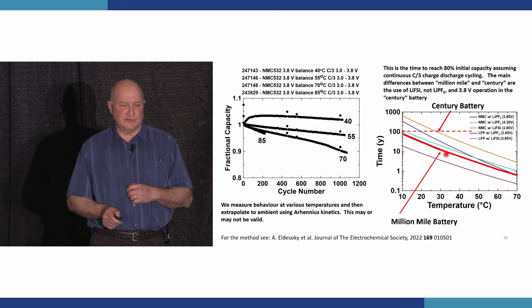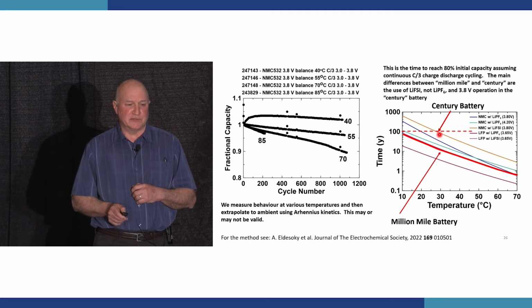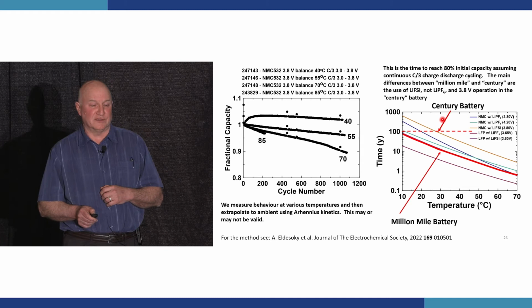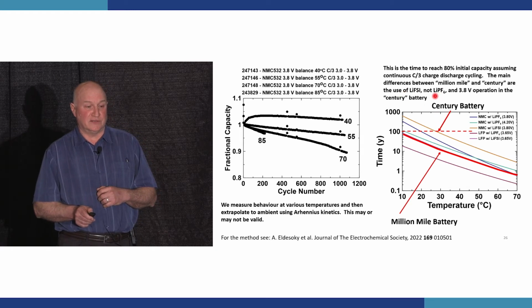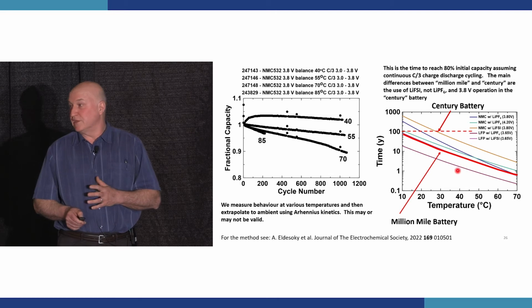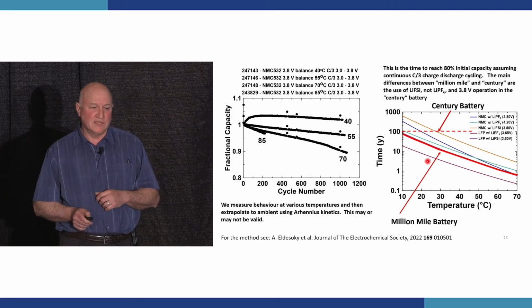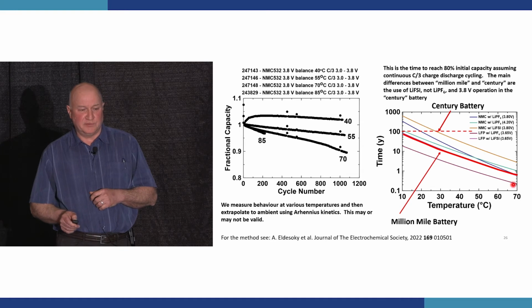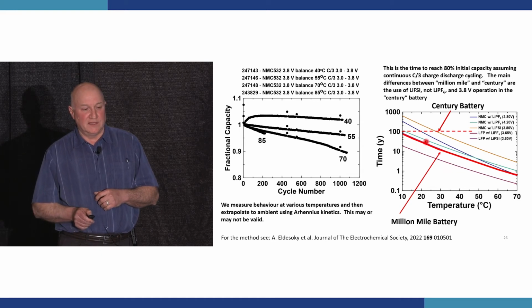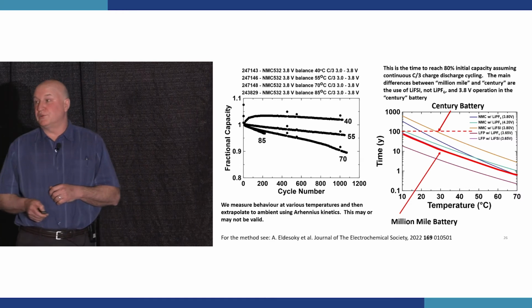So what's actually the difference between the million-mile battery and the century battery? It's almost nothing, really. It's a change of the electrolyte salt and operating at lower voltage. And that just boosts the lifetime up a factor of 10, okay? So even if these extrapolations are not valid, I still believe it will boost the lifetime a factor of 10. And then where's LFP on this chart? LFP with LiPF6 is at the bottom, and LFP with LiFSI is this curve right here, okay? So this is pretty incredible.